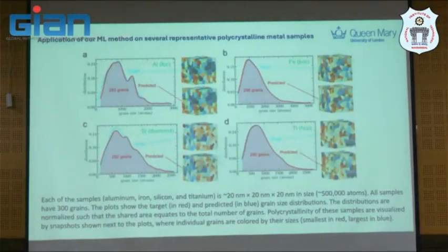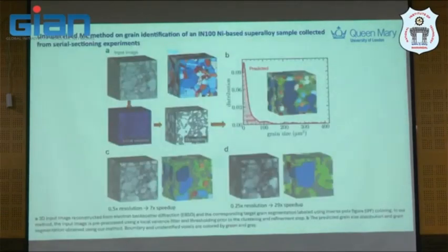So this method has been used to represent different crystalline materials in metal. It's not just nickel-based superalloy. It's also used in aluminum alloy, FCC, iron, silicon, and also titanium as well. So you see that the size of this is quite good, that they can learn and then represent the structure in 3D. And what it's used for is to get the predicted grain size against the actual grain size in the Inconel 100 nickel-based superalloy here.